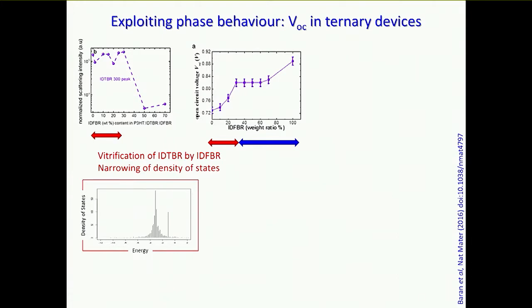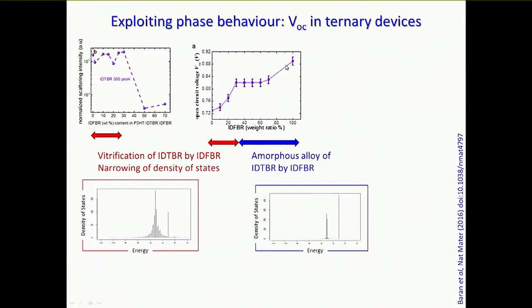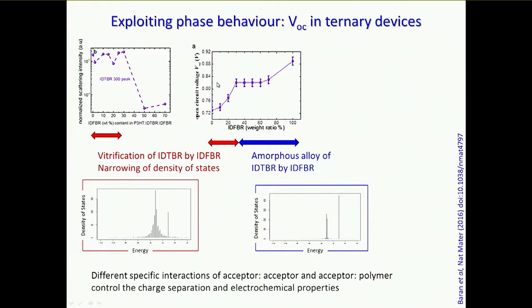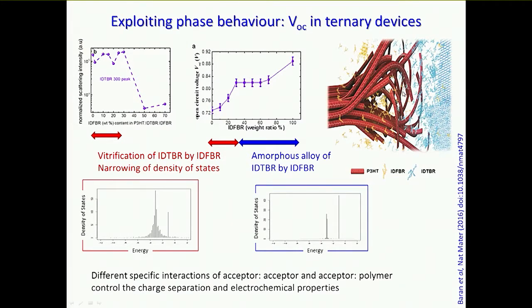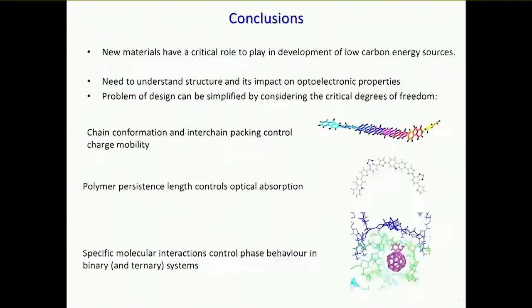And then when you get past that point, you simply have an amorphous mixture. What you observe in the VOC is the trend you would expect from a simple alloy of one thing in the other, so that at the very extreme of one component, you shift to the higher band gap limit. So this is what we think is going on. It looks like hose pipes to me, but my colleagues generated this image to try and illustrate what's going on: you've got one component whose specific interaction with itself is weaker compared to its interaction with the other components, and then it serves the purpose of controlling the microstructure. So it's just an example of the sort of thing that could be possible if we understood these specific chemical interactions. So finally, I can finish.